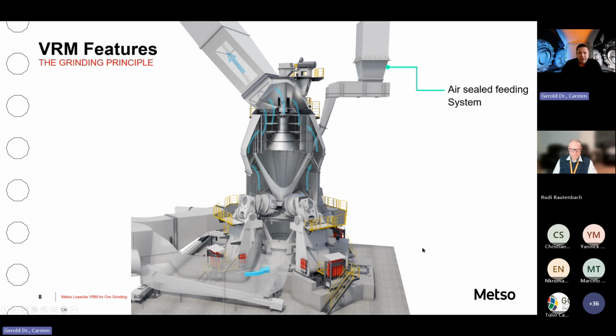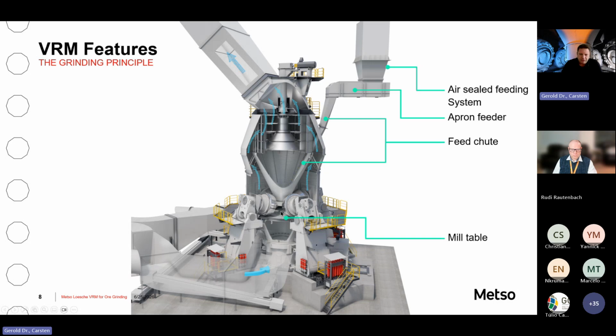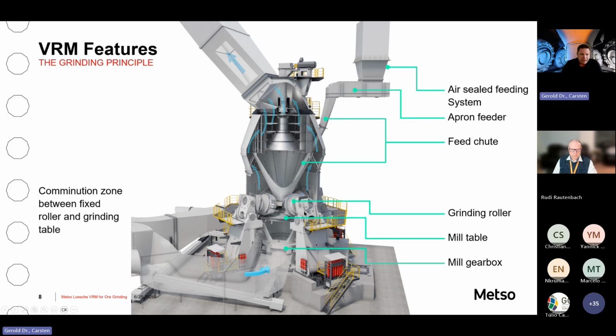The way it's built up, remember, we are in negative pressure, so we need an air sealing system, which is achieved by that feeding bin. We have an apron feeder, which could also be a cross belt. From there, we feed the material onto the center of the grinding table via the feed chute. The mill table is driven by the mill gearbox and the mill motor, and then we have the grinding rollers, which are fixed. The comminution zone is between the fixed grinding rollers and the turning table. At the bottom, you see the gas inlets.